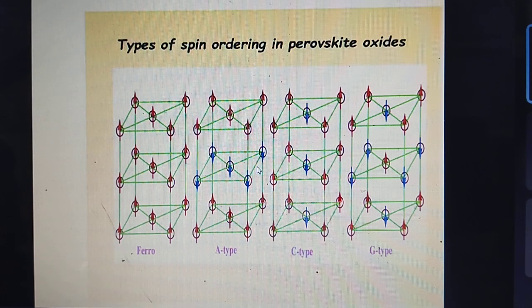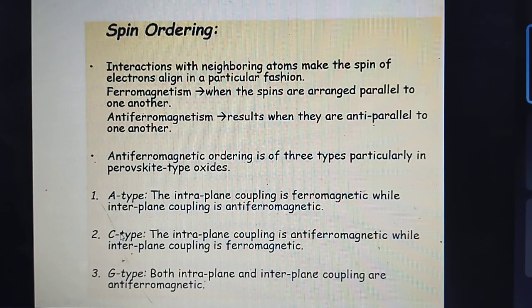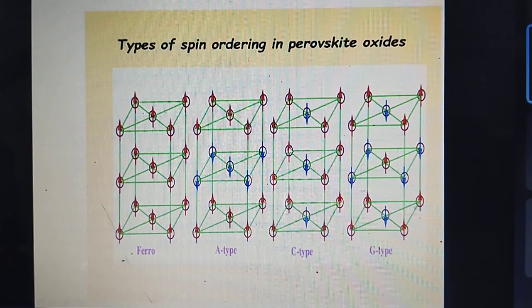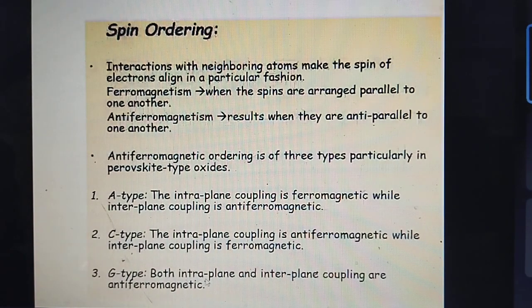So this is all because of Mn3 plus or Mn4 plus, which are getting ordered. So this is intra, they are in the same direction. Inter, they get opposite. This gives rise to the A type antiferromagnetic material properties. C type, the intraplane coupling is antiferromagnetic, while interplane coupling is ferromagnetic. So this is the reverse of this one. You can see this is in the same direction, whereas this is in the opposite direction. And G type, both intra and interplane coupling are antiferromagnetic.